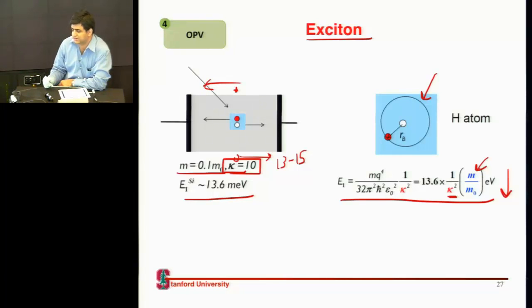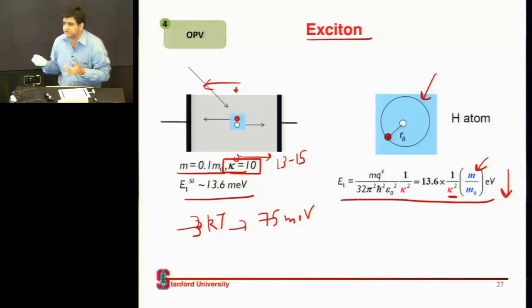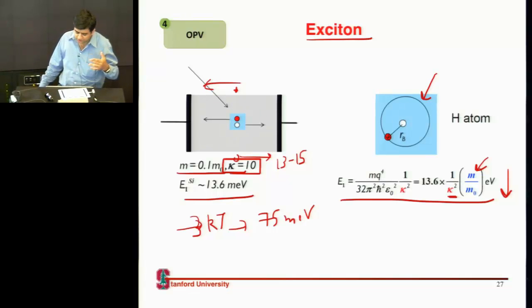And this is much less than even the free energy you have available at room temperature. 3 kT would itself be 75 meV. So I can easily thermalize these, and they will separate into electron and hole pairs, which can flow in different directions. This is the reason why we always treated them that if you generate an electron and hole, you can collect one easily at one contact and the other at the other contact. But this is only true for these semiconductors.